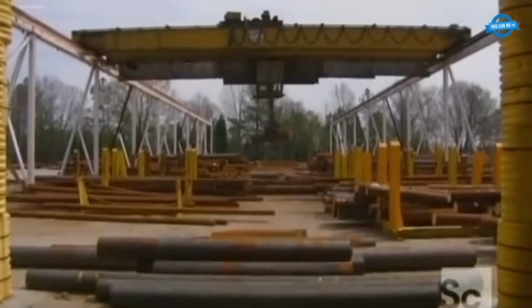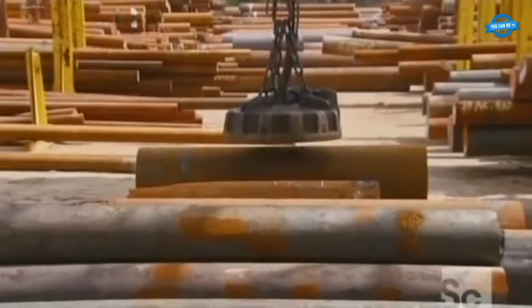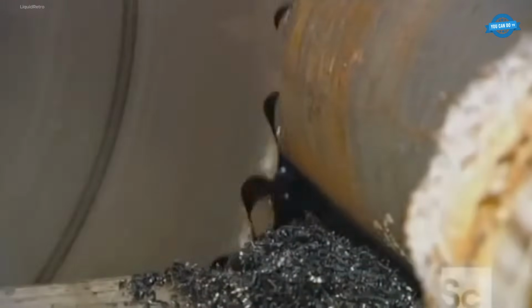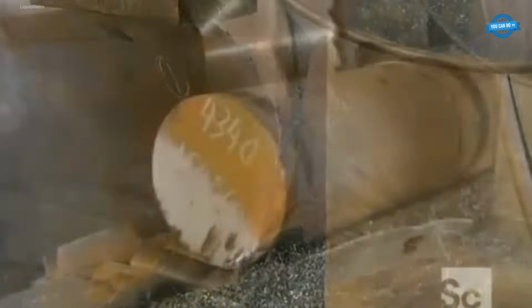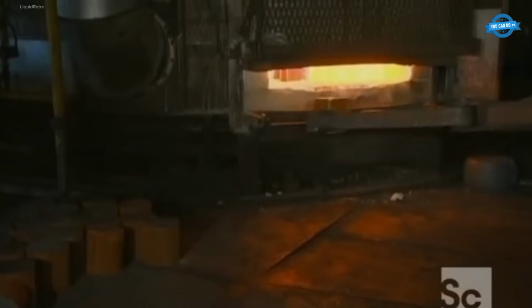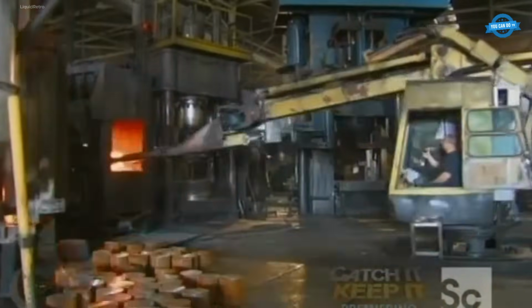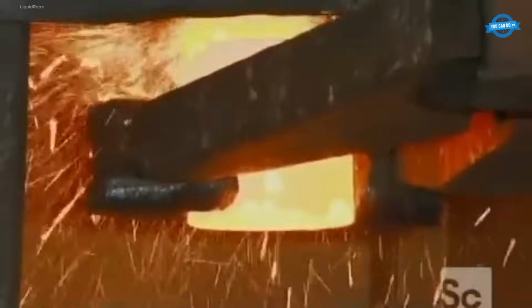The process of making seamless steel wheels begins with magnets moving solid steel billets into place. A carbide-tipped saw cuts the billets into smaller blocks. A hydraulic ram carries each block to a 2,300 degrees Fahrenheit furnace to soften the steel. After heating, the ends are descaled in a chamber with a chain beater. The steel is then pressed under an 1,100-ton press to further remove the scale.